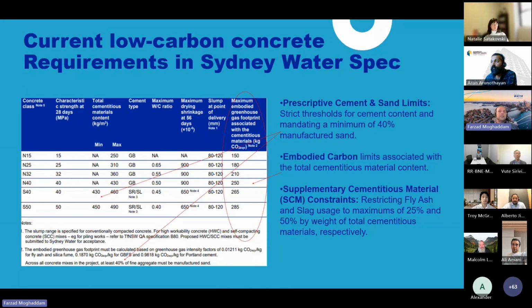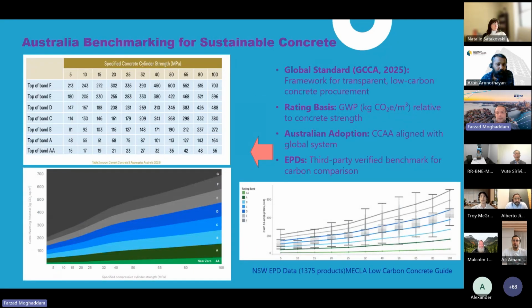That is the current situation in our spec, but we are trying to change and move toward letting suppliers have more freedom in using more fly ash and slag. In our next revision, they will be able to use up to 30% fly ash and up to 60% slag, so we are pushing the boundary a little bit on maximum cementitious material. We are also changing this column: we are going to come up with a maximum embodied carbon for 1 cubic meter of concrete, which I explain in the next slides.